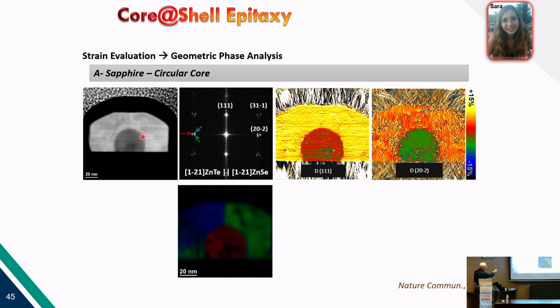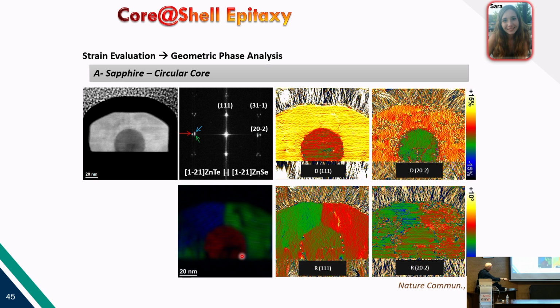When the core is cylindrical, in the cross-section it is like a closed circle, and you are growing the shell on top, you see that the shell needs to adapt to the core. And in the case of this shell, when it's covering the core, you see that this is a kind of rotation map in which you see that at both sides of the shell, you have a ±2 degrees rotation. So the shell tries to adapt, and adapts by flexing a little bit.